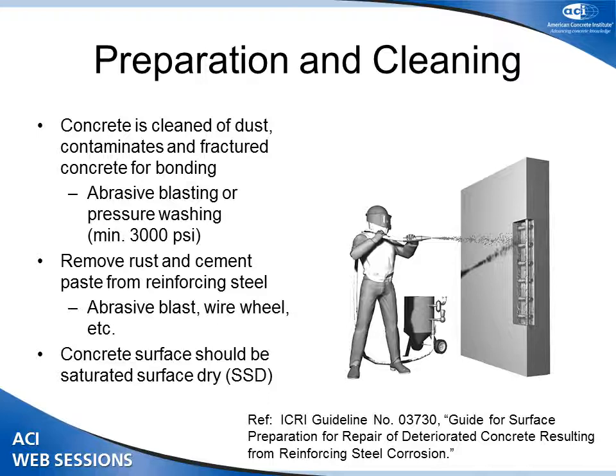You're going to wet the concrete, the base concrete, to the point where it's wet or saturated, but not glistening on the surface, where the surface is somewhat dry. And because many of these repairs are thin repairs, you don't want a lot of moisture from the repair material being sucked into the base concrete, which would dry out the material and affect its durability. So saturated surface dry condition is typical, but refer to the manufacturer's data sheets.